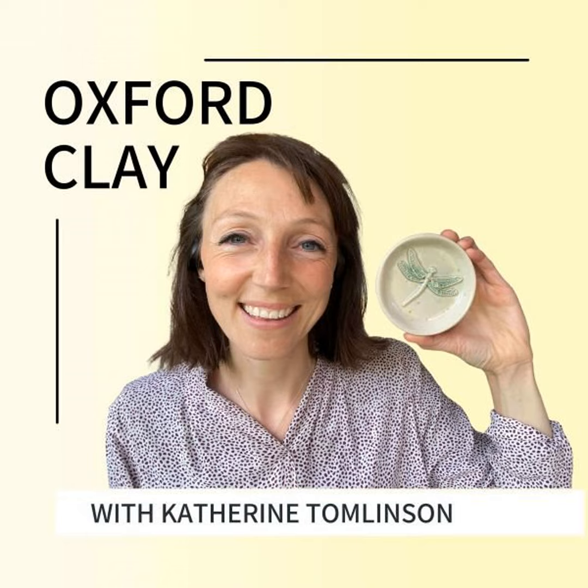And what I found was that it actually started to burn out some of the colour, because I use verdigris, which is quite a gentle colourant, and I found that it just burned away a lot of the colour. So I think 15 minutes is my optimum soak time at that extremely high temperature, and that allows the glaze to melt really nicely.